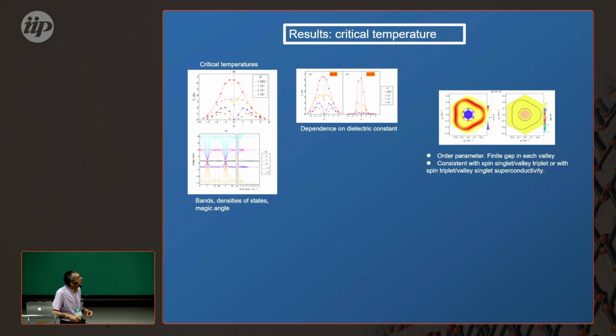We got superconductivity. The critical temperatures were on the order of a few Kelvin, which is not bad. I have to warn you that you should never trust a theoretical estimation of a single critical temperature, because it depends exponentially on many uncontrolled parameters. So it's not a very quantitative prediction we can make, but we can identify trends—that's a different matter.